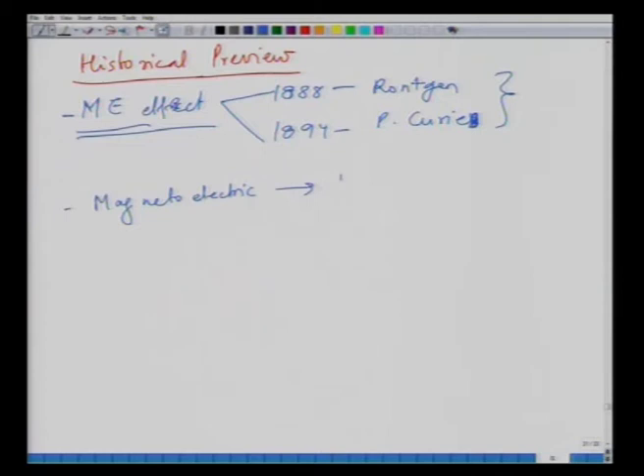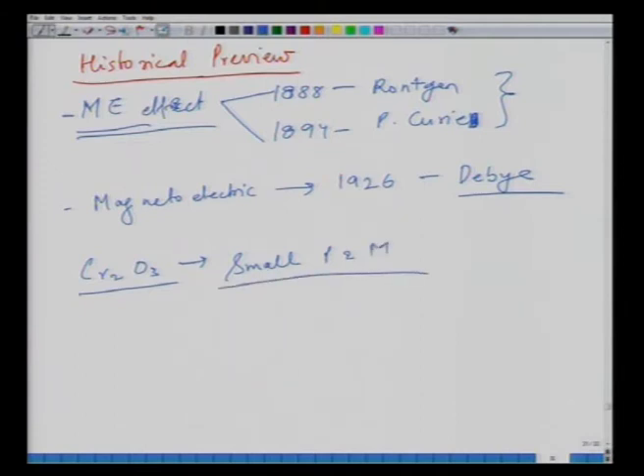So the term magnetoelectric was used in 1926 by Debye. This was the first time when the term was used, and the first material to show this effect was chromium oxide. And this chromium oxide showed small magnitudes of induced polarization as well as magnetization. So you can say small P and M, and after that there was a flurry of activity and a variety of other materials were discovered to show this, for example Ti2O3, and gallium ferrite was again studied, and then boracites, phosphates, etc. A variety of these materials were studied for the magnetoelectric effect.